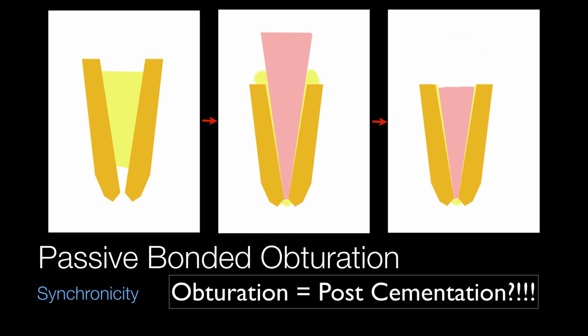And the benefit of this particular type of passive obturation technique is the idea that you're not really putting too much excessive pressure on the canal walls with your spreader or with your condenser. One of the biggest problems with those active obturation techniques in the past had been the idea that you are not only widening the canal too much in order to fit your spreaders and condensers, thus unnecessarily removing good tooth structure, but also you were putting active force into the root, right in the cervical area where you had thinned out completely because of your excessive taper, you would end up putting too much pressure and potentially crack the